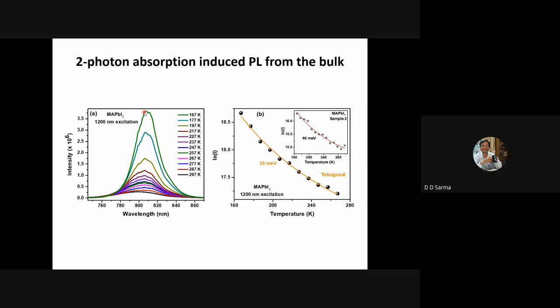And these are very stable data. Two-photon absorption induced photoluminescence, and then we see how the photoluminescence changes. Then we extract the number, and the numbers for two different measurements are 55 meV and 46 meV for two different samples of the same composition. That tells you the sort of error bar. So it's 50 plus or minus 5 or 6 millielectron volts, the excitonic binding energy.